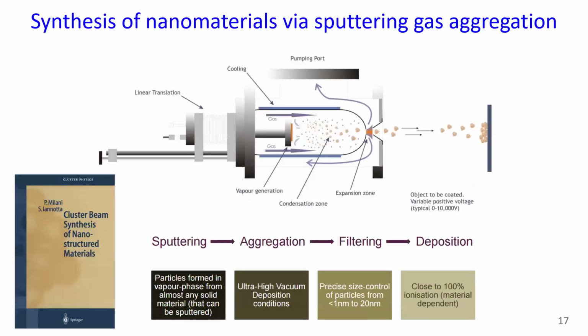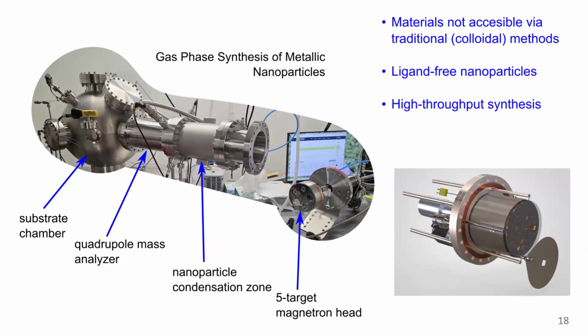Do you have a sense of whether these Janus structures form in the gas phase or when they're on the surface? Oh, that's a good question. What if you rapidly cool the surface? The sample stage we're getting will have heating and cooling capability, probably not a huge temperature range. A lot of times for solid state synthesis, doing this in a tube furnace, you're changing the temperature to hundreds of degrees centigrade, thousands. So I don't know if the temperature will be high enough to enable atomic diffusion.